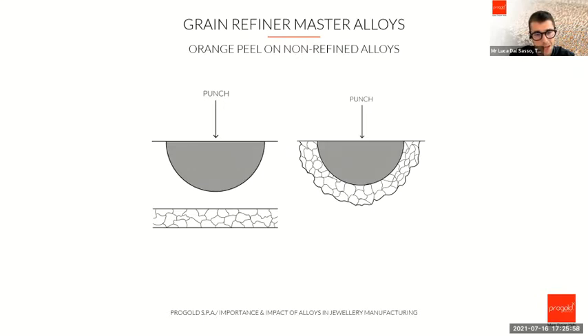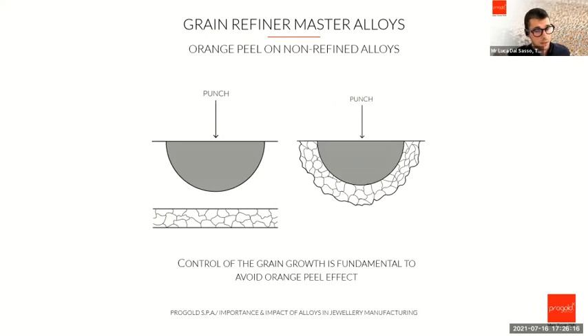You can see that the surface is not smooth anymore once deformed. And so imagine how the smaller grains can make it really smoother. Imagine how much less deep these big holes in the surface of the piece would be. And this is possible thanks to the control of the grain growth, which is a really great advantage of the fine grain master alloys.